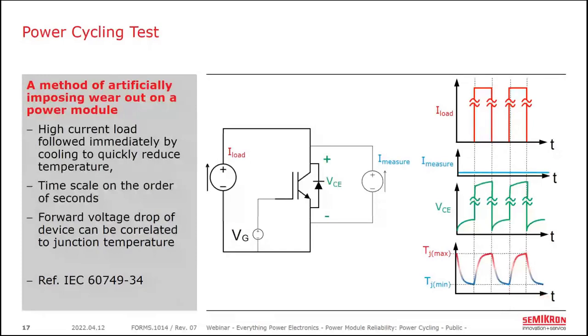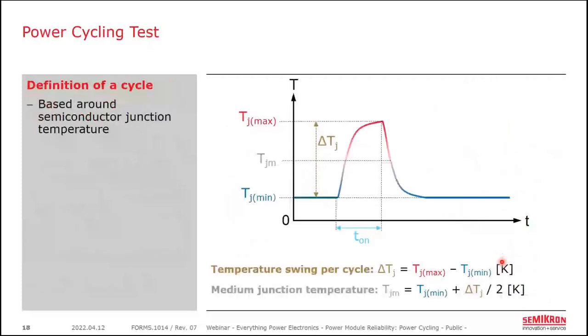Now, this definition of minimum and maximum needs a closer look because it's going to be the basis for the predictive model that we discuss in a moment. So, power cycling is defined in terms of the semiconductor junction temperature. We're talking about the junction of the device.